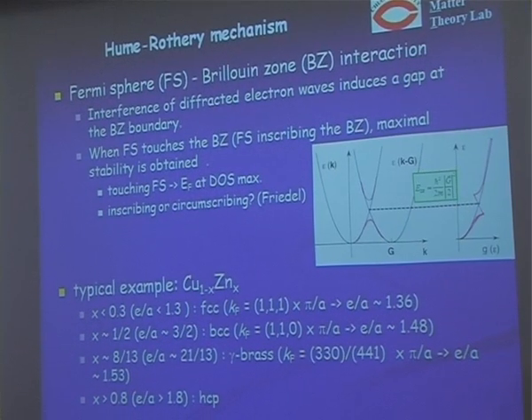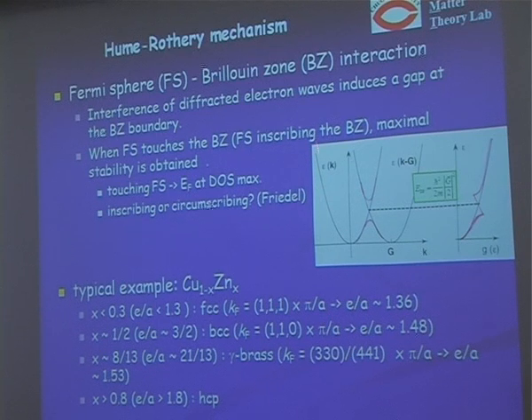In the Hume-Rothery mechanism, the key concept is the Fermi sphere-Brillouin zone interaction. In crystals or ordered materials, electrons are diffracted, and interference between the diffracted waves induces a gap at the zone boundary. Here I have the dispersion curve for the nearly free electrons, and we have dispersion curves for the diffracted waves. And at the crossing point, we have the gap open.